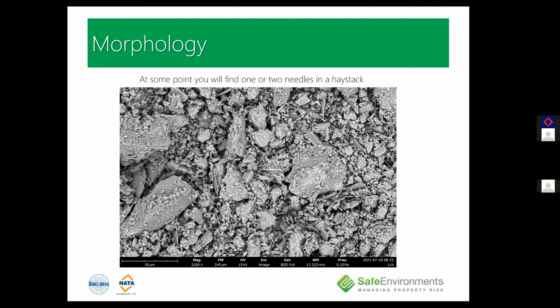What can be concerning is failing to place results into context. Where there are the elements that make up asbestos, there is the opportunity for asbestos to be present. What can also occur is the apparent creation of what seemingly appears to be asbestos from crushing or grinding material during sample preparation. A single acicular needle does not amount to the identity being confirmed as asbestos, and further assessment of the crystalline habit en masse needs to be considered.